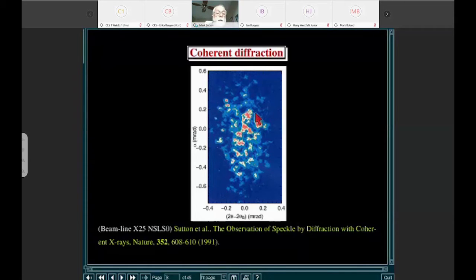There's the size of the red spots, which in some sense is 2 pi over the size of the beam, and there's the size of the envelope of the scattering, which is 2 pi over the distance between the domain walls, or the size of the grain boundary regions, which are creating the scattering in copper-3 gold. So this is just a static pattern.